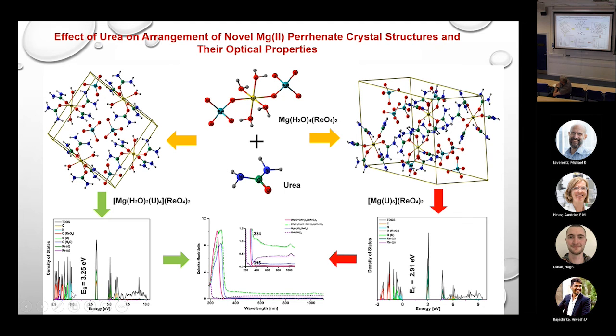We found that the conduction band consists of oxygen and nitrogen states of urea, and when the number of urea ligands increases, going from urea 4 to urea 6, the energy of the conduction band increases. This is why the band gap decreases. The valence band consists of perrhenate states, and they are constant. There are no changes in it.